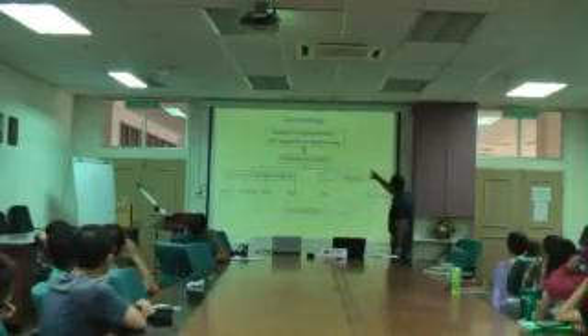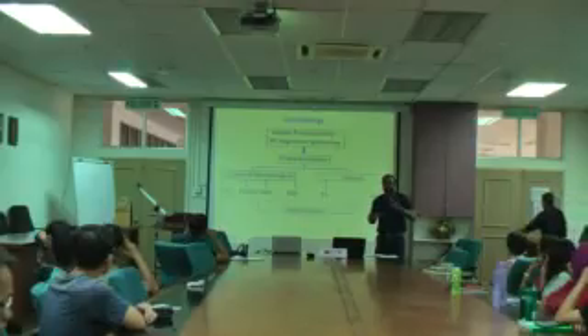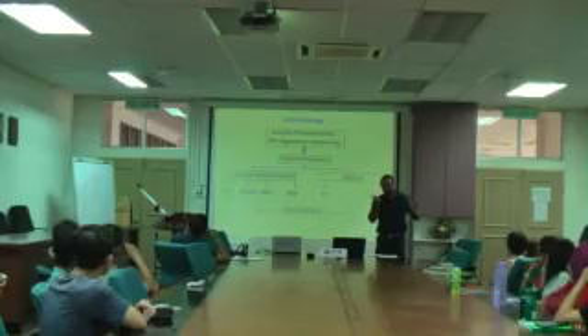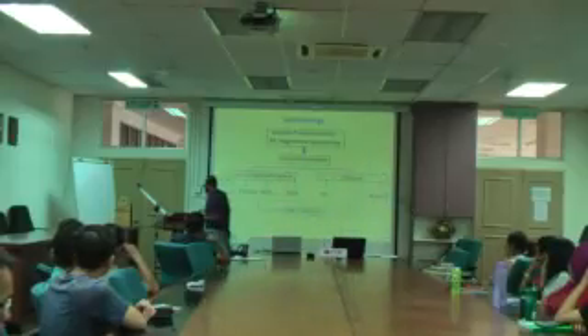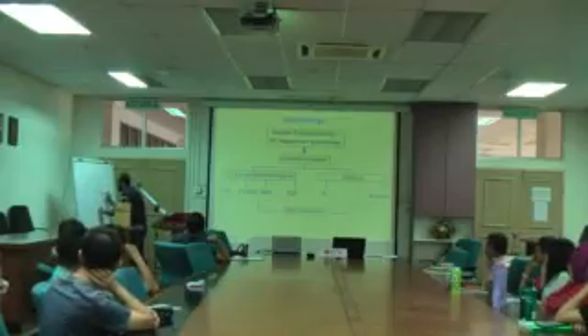So this is our methodology. First, we prepare 3 kinds of samples. The first category has a different annealing temperature, and we keep the other parameters constant. What are the other parameters? The germanium thickness and the silicon oxide thickness. If I want to explain, we have a heterostructure like this. The first layer is silicon, the second layer is SiO2, and the third layer is germanium.